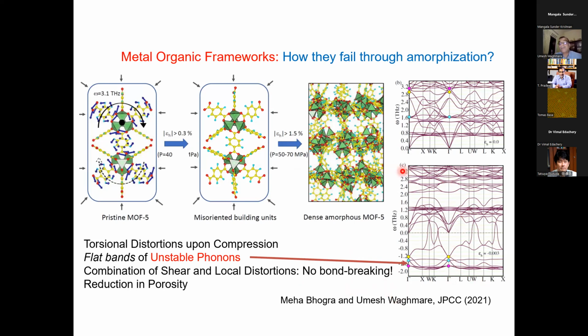So this, of course, affects functionality, meaning there's a great reduction in porosity, which is very important to application of metal organic frameworks. So this is something similar we have shown in ZIF8, another prototypical MOF structure, but there the pressures are a little higher than what are involved in MOF5.